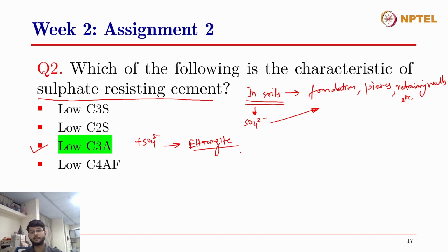And ettringite is a crystalline material. It occupies a larger volume than the aluminate itself, and therefore it occupies the voids that are present and provides us strength. When the concrete is in a plastic or fresh state and ettringite is formed, there is enough void volume to accommodate this ettringite formation, and therefore it will provide strength to us.